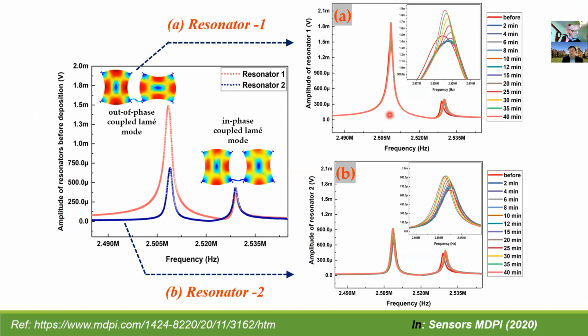So when I was doing this experiment, the frequency peaks didn't appear to shift with increase in particle deposition. So I wasn't sure if the resonator was sensitive at all to the particles deposited. But when the response was zoomed in, it clearly showed the small shift in frequency and amplitude depending on the mass of the particles deposited.